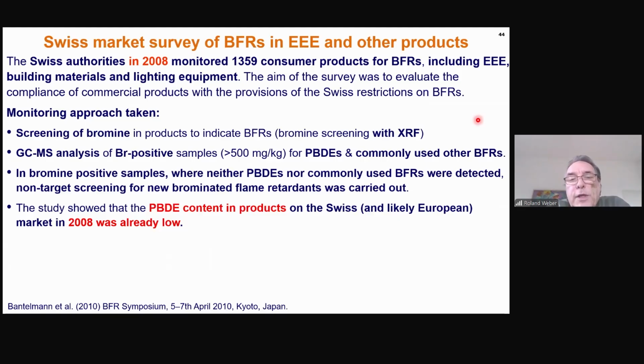Then a second best practice study is from the Swiss authorities in 2008. They monitored 1,360 consumer products for brominated flame retardants, including electronics, building materials, and lighting equipment. The monitoring approach taken was also first to do a screening of products with the XRF, then to analyze with GCMS the bromine positive ones, which had more than 500 milligram per kilogram, and they analyzed PBDEs and other commonly used brominated flame retardants.